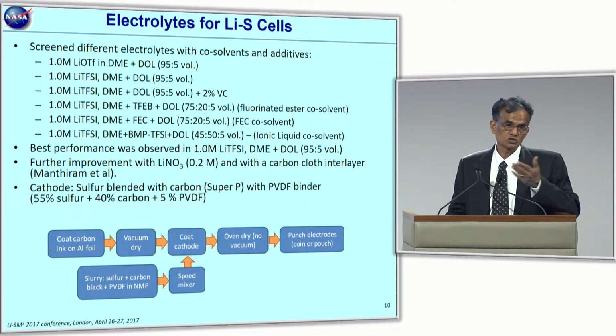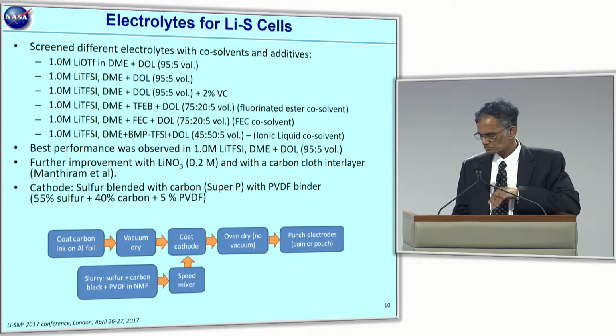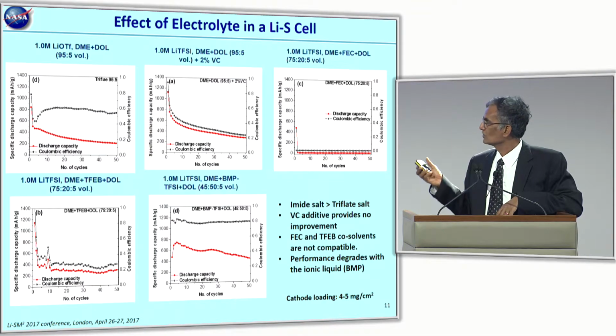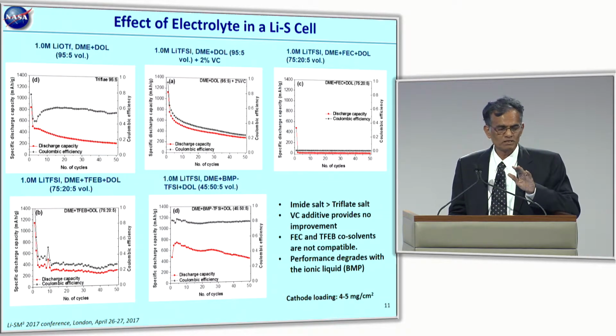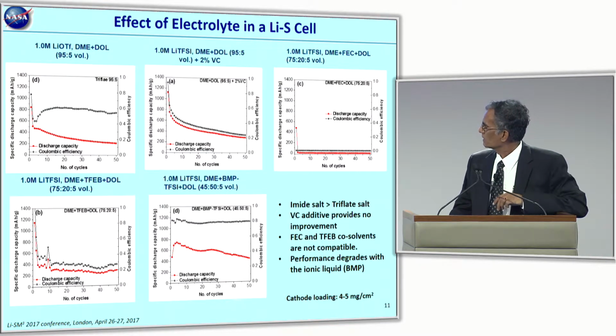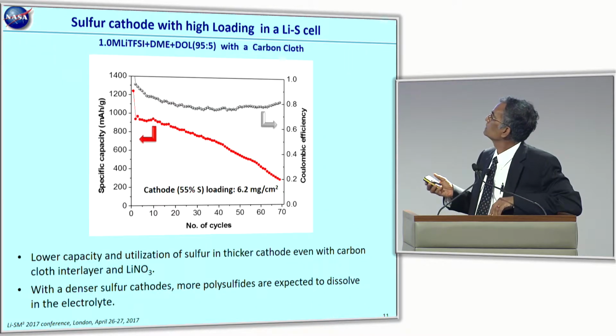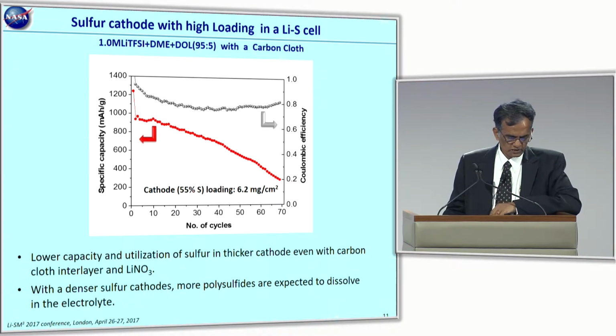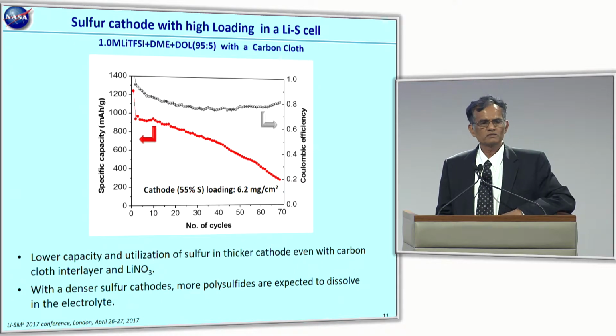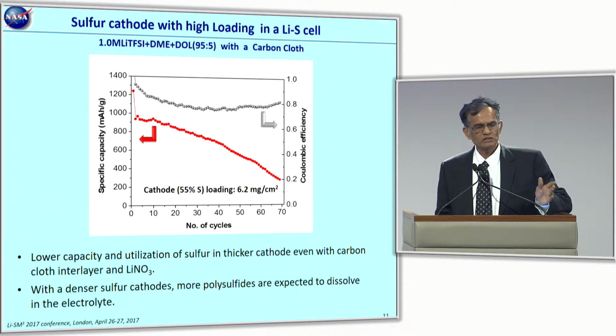We tried those things here, and also the combination of ionic liquid, and our results show that the best combination, of course, in all these cases, you can see that we haven't seen the performance that we typically see with the TFSI salt and with this simple DME-DOL blend. And so we stuck to what we have right now, which is, as I said, the blend of these two solvents with TFSI. However, we also have the standard lithium nitrate, 0.2 molar. And we spent quite a bit of time trying to get some decent reproducible data from this lithium-sulfur chemistry.